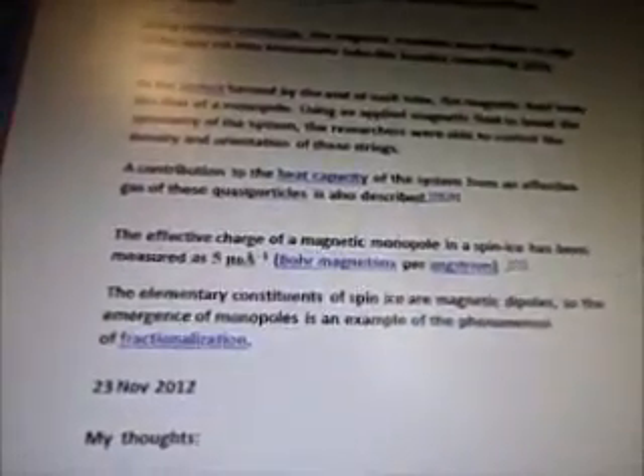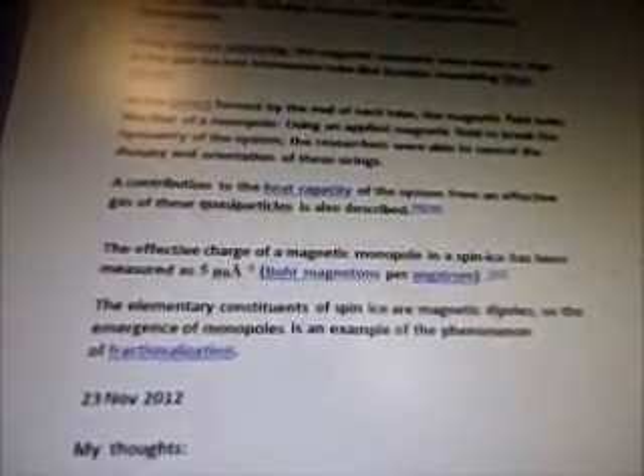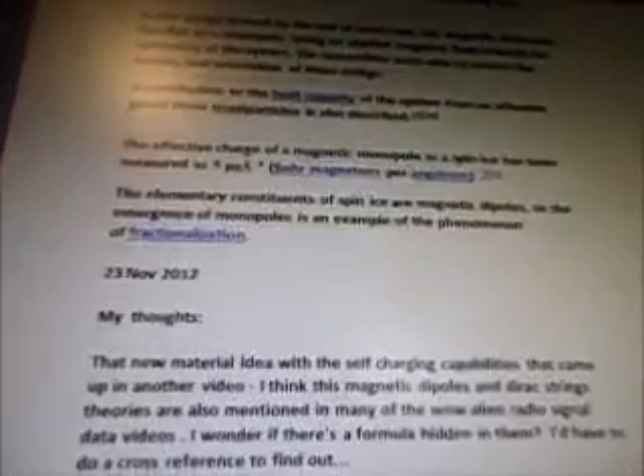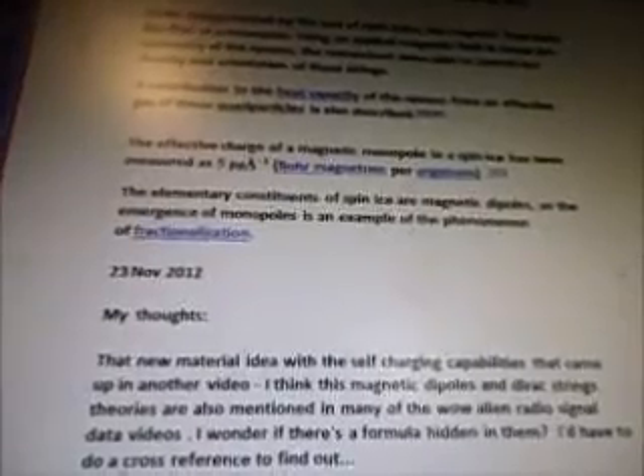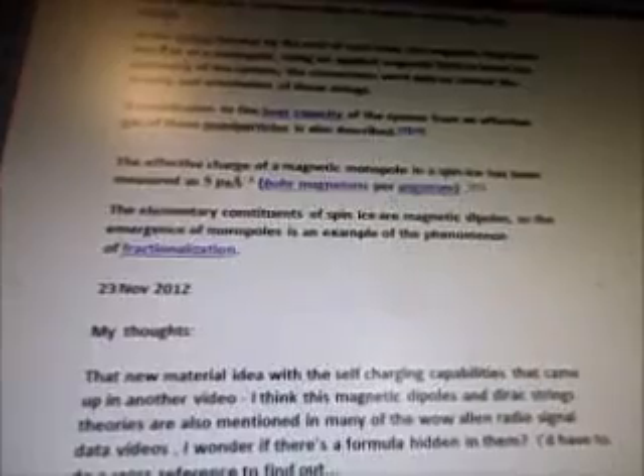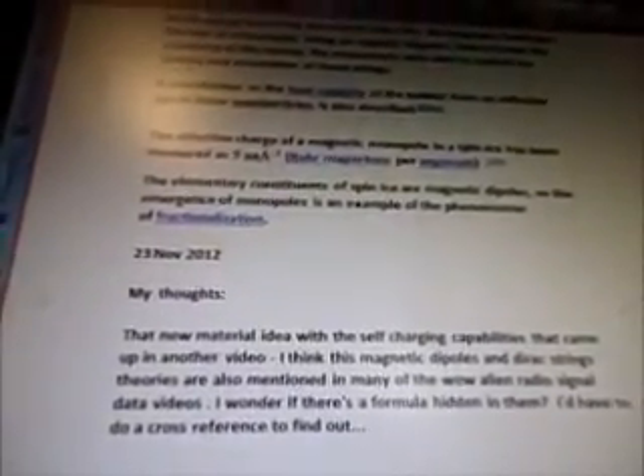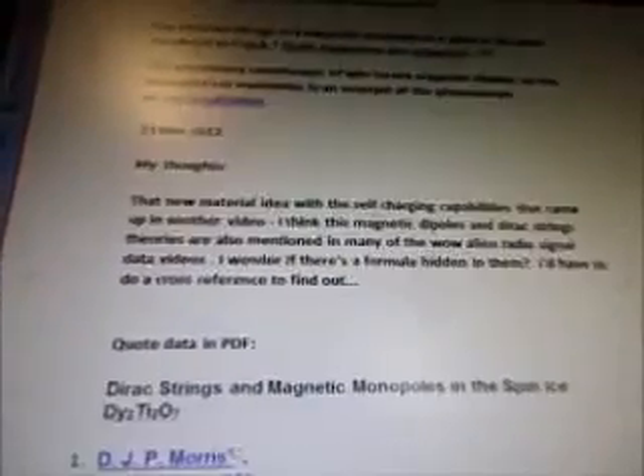Using an applied magnetic field to break the symmetry of the system, the researchers were able to control the density and orientation of these strings. A contribution to the heat capacity of the system from an effective gas of these quasi-particles is also described. The effective charge of a magnetic monopole in a spin ice has been measured as 5 μB per angstrom. The elementary constituents of spin ice are magnetic dipoles, so the emergence of monopoles is an example of the phenomenon of fractionalization.